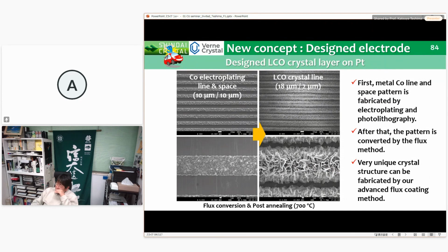With our flux coating method, we can make various designed crystal layers. These are cobalt metal electroplating line and space patterns, and LCO crystal lines. First, cobalt metal line and space patterns are fabricated by electroplating and photolithography. In this case, these patterns act as a solute. After that, the pattern is converted by the flux method. A very unique crystal structure can be fabricated using our advanced flux coating processes.